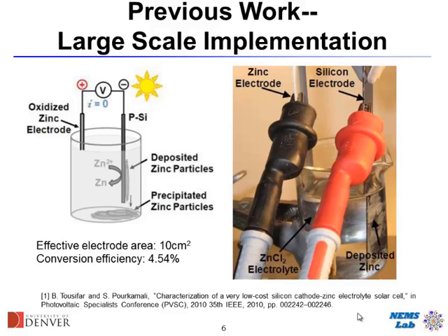We tried silicon along with different types of solutions. One of the things that turned out to be working pretty well is a zinc solution. So what we have in this setup is basically a zinc electrode, which is dipped inside a solution of zinc chloride. And then we have the silicon electrode, which is the photo-cathode in this case. We are using p-type silicon, and the reason is that, well, I'm going to get to that later on. So we have a p-type silicon next to the zinc electrolyte and the zinc electrode.